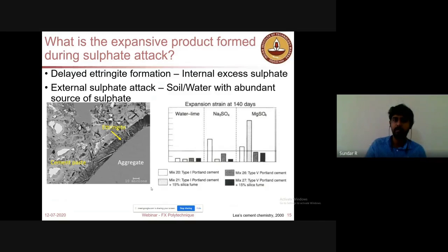So now for sulfate attack, this is due to the sulfate presence in the external as well as the internal. So when the cement matrix has a source of sulfate, that sulfate later will react with some hydrated phases and then form the expansive product called ettringite. This ettringite will create micro cracks inside the cement matrix and reduce the strength. Also external sulfate attack refers to the water or soil, when the concrete pier is present inside muddy soil which has sulfate. So you have a lot of sulfates around your concrete, and that sulfate can come into your concrete and create the sulfate attack.